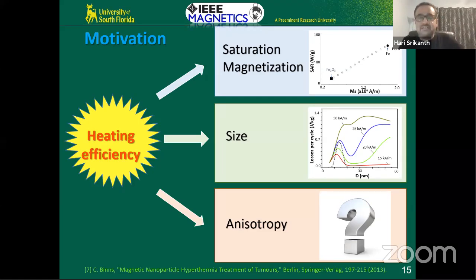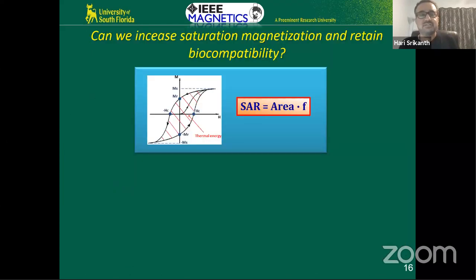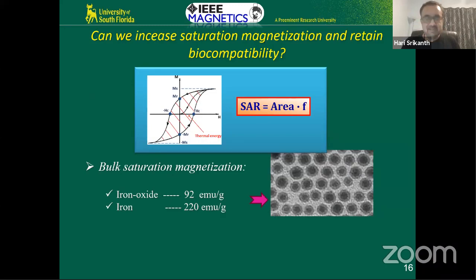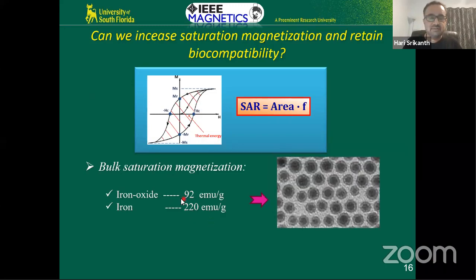Okay, but first, let's talk about this one right here. Can we increase the SAR somehow, making a particle with larger saturation magnetization? We can do that if we do a hybrid particle, right? For example, we can go to core shell particles. And by core shell particles, I mean, if you take an iron core, right? Iron has a large magnetization. And of course, the shell, if the iron is completely encapsulated by an oxide shell, then it's biocompatible, right?